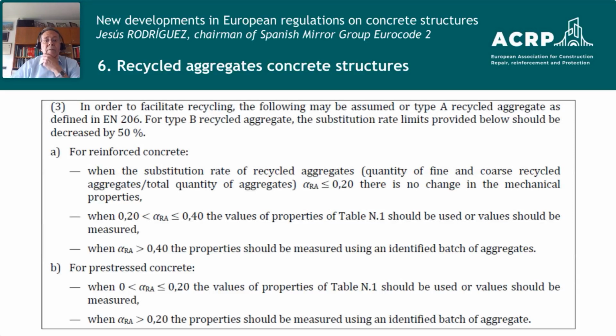There are two types of recycled aggregates, A and B, defined depending on where these recycled aggregates come from. In the case of A, it is a high quality aggregate, and here we have recommendations. In the case of B, these recommendations need to be reduced by 50%. And it is said that with A recycled aggregate replacing less than 20% of the total aggregate,